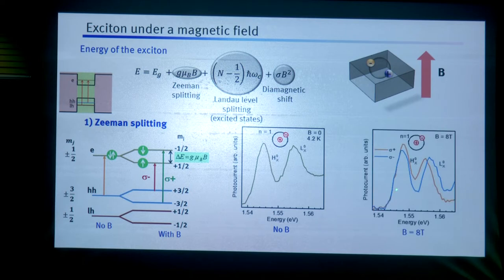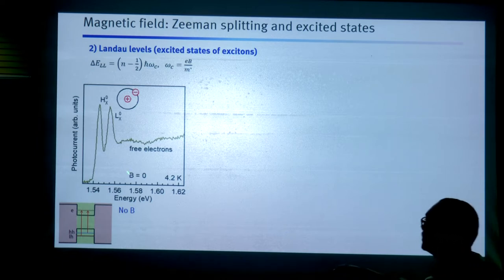Now let's see, when we do circular polarization resolved spectroscopy, this experiment was done in TIFR when I had just started my PhD. So this was under 8 Tesla, and we made these 2 graphs. One is sigma positive, left circular polarization. This is right circular polarization, and then there is Zeeman splitting. Okay. Now this is simple, Zeeman splitting. But what happens in this region?